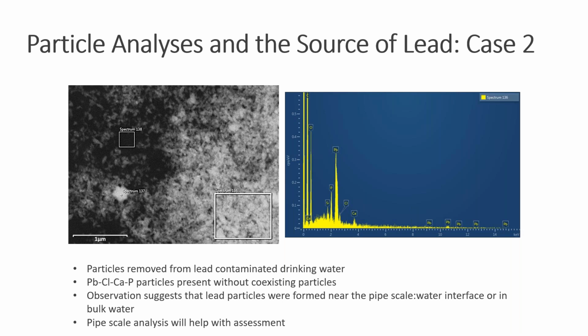Whereas this is case study 2. When you look at this one, in all the samples we looked at from this particular location, these are relatively uniform, really small particles, and there's nothing else really there. Again, this is a contaminated water situation. This sample was very high in total lead, but soluble lead was very low. And again, we find the same kind of situation. We find lead, chloride, calcium, and phosphorus associated with these particles. So maybe it's the same calcium substituted chloropyromorphite type of particle, but nothing else.